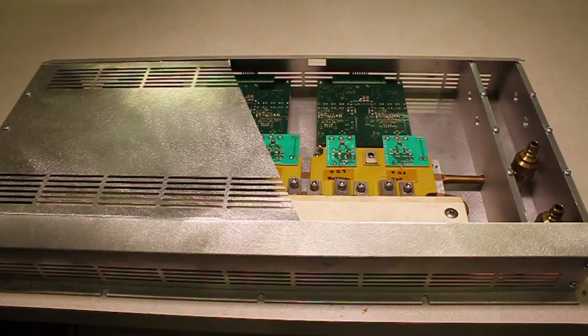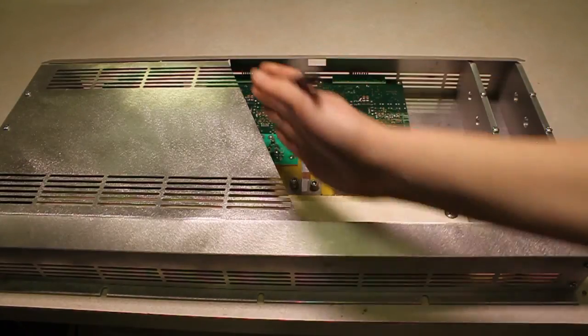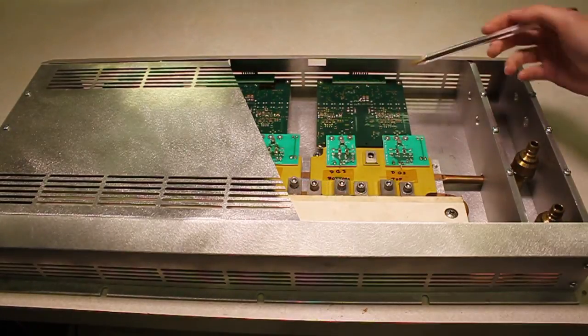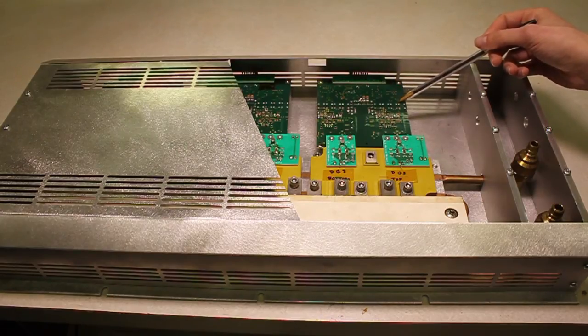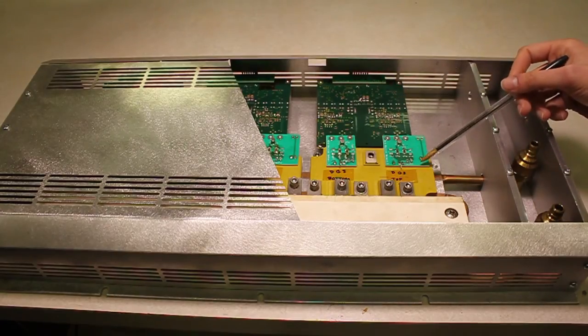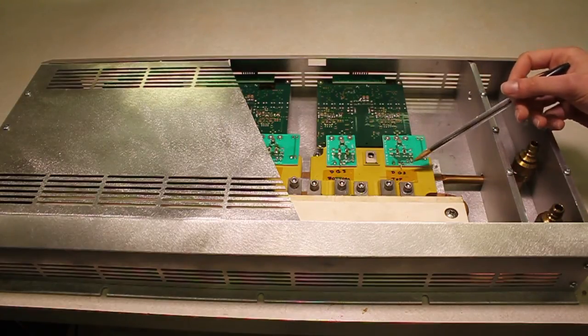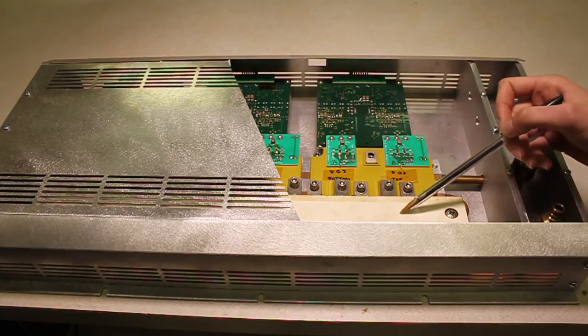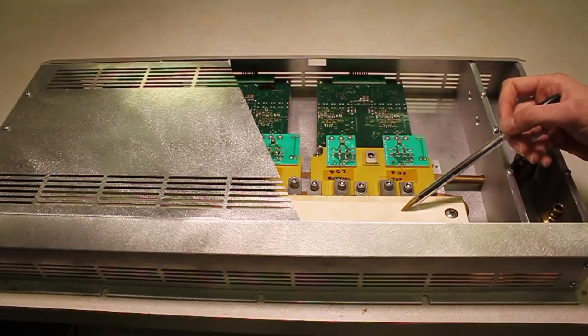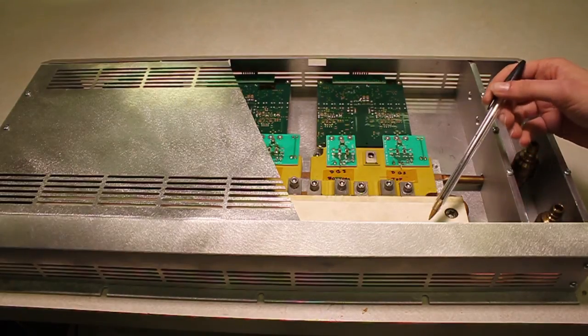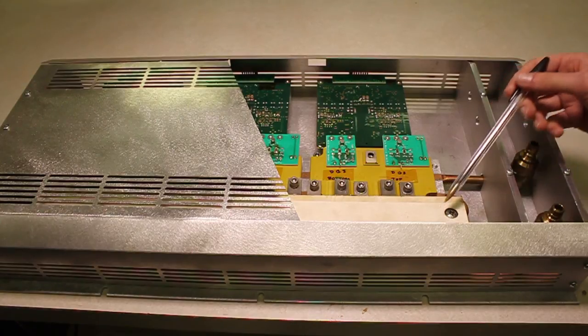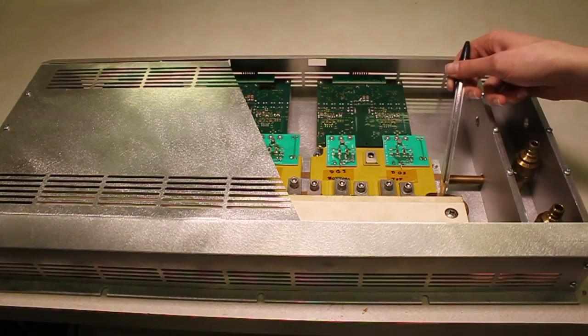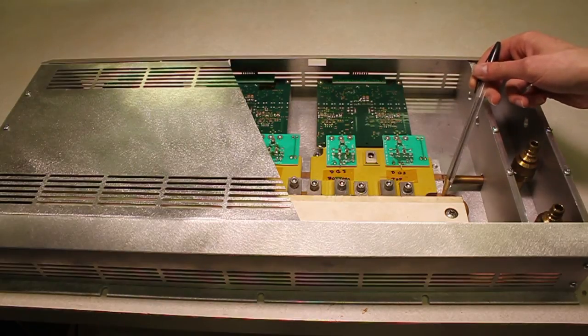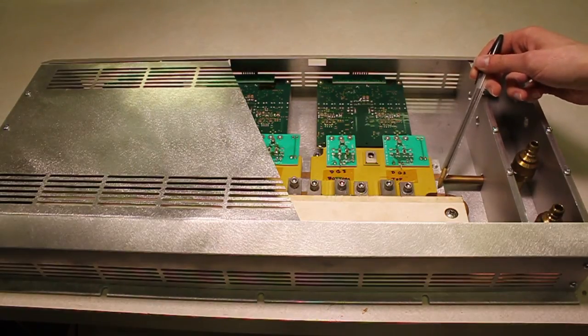This is the assembled high-temperature 50 kilowatt AC to DC bidirectional 3-phase converter, with the motherboard removed and the lid partially cut. In this way, you can see the high-temperature gate drive from SiC connect to the high-temperature power module through a gate resistor board. The power module is then connected to a laminated high-temperature DC bus bar with the DC link capacitors mechanically connected underneath. The ceramic capacitors and the power modules are on top of a 70 degree C liquid-cooled cold plate.